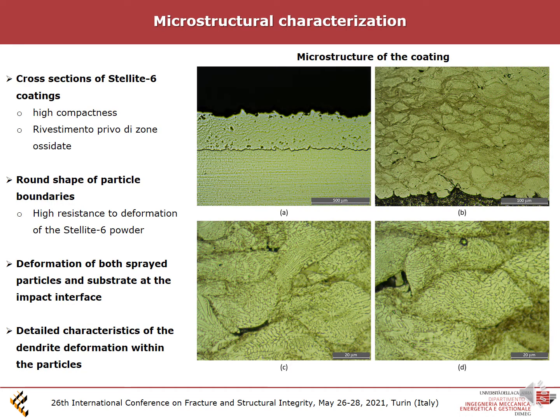The cross-sections of the obtained Stellite-6 coating are presented in this slide, and how you can see from the higher magnification images, the particle boundaries maintain their round shape, and this result can be related to the resistance to the deformation of the Stellite-6 powder. Moreover, the deposition mechanisms involve mechanical deformation of both sprayed particles and steel substrate at the impact surface, as a consequence of the higher Stellite-6 hardness compared to the steel substrate. Moreover, are also shown the detailed characteristics of the dendrite deformation within the particles that are typical for the cobalt-chromium system.